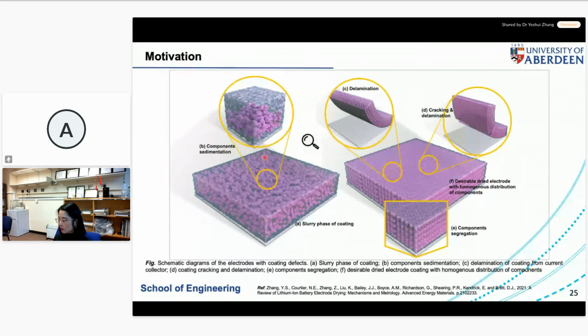If the process is too slow, we could have component sedimentation. Ideally, we want everything to be distributed homogeneously, but if you dry it too slowly, we cannot reach a homogeneous structure. And if you dry it too fast, the binder will be driven, because the solvent will evaporate, and this will drive the binder to the top layer of this electrode or this coating. In that case, you move all of this binder to the top, with less binder at the interface between the current collector and the coating. So you have delamination of this coating and other types of defects.